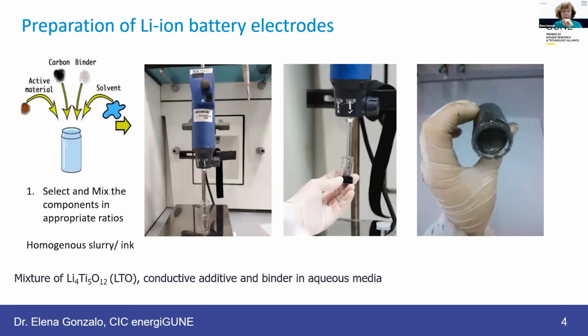As some of you are not familiar with the steps we have to follow to prepare these electrodes and the role that the current collector plays in these steps, I will briefly summarize those steps. The first part is to get a homogeneous slurry, a homogeneous mixture of the active material, that in our case was an oxide of lithium and titanium, the LTO, and the conductive additive plus a binder to attach the three components to each other and also to the current collector. In order to do that, we need to use a magnetic stirrer, as you can see in the pictures, and we got this final result, a homogeneous ink with a particular density.